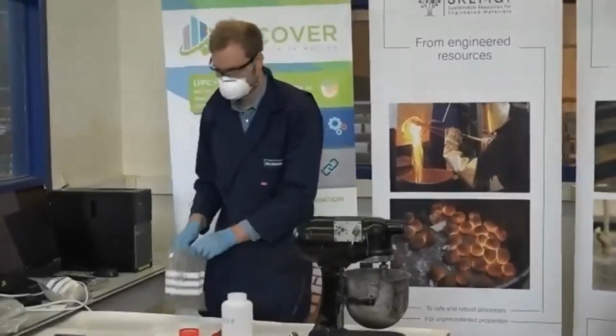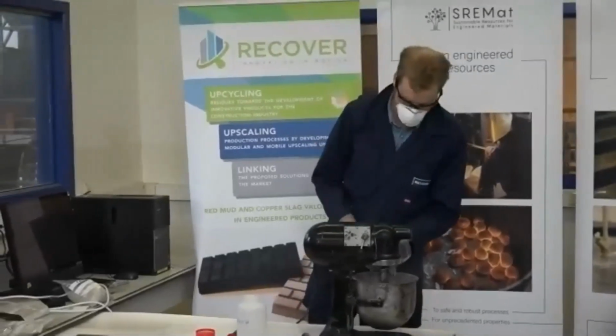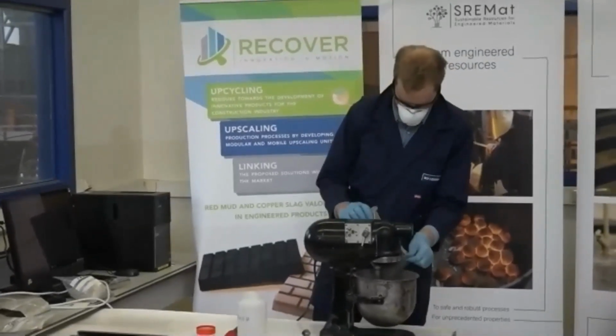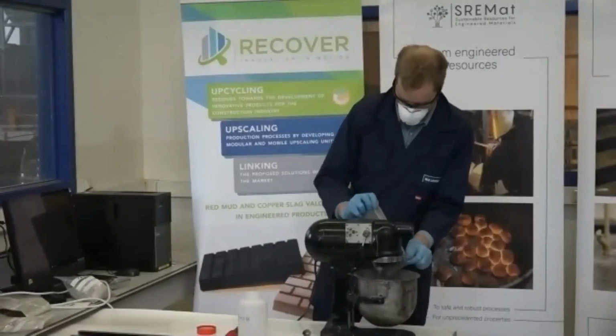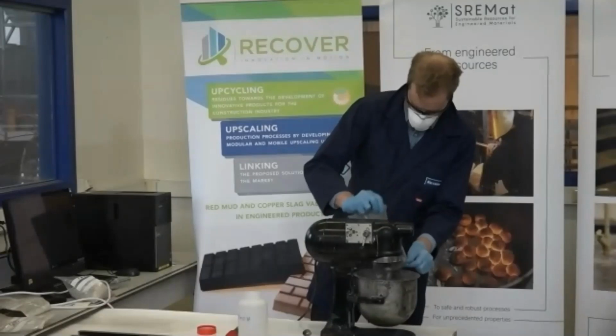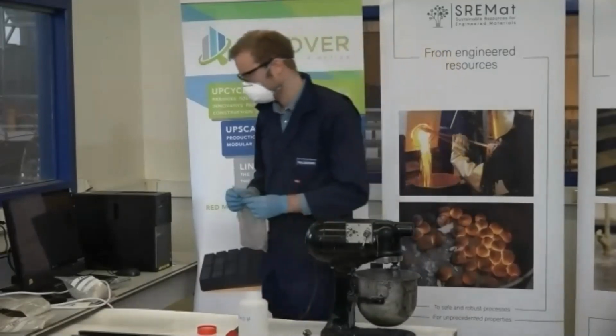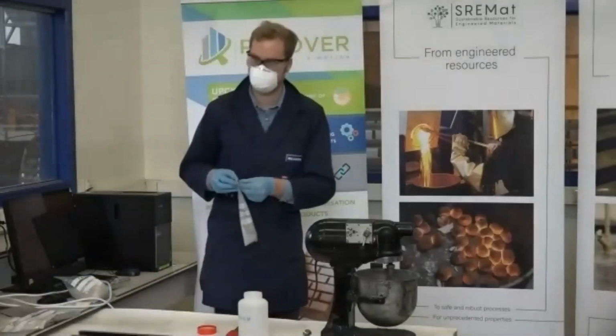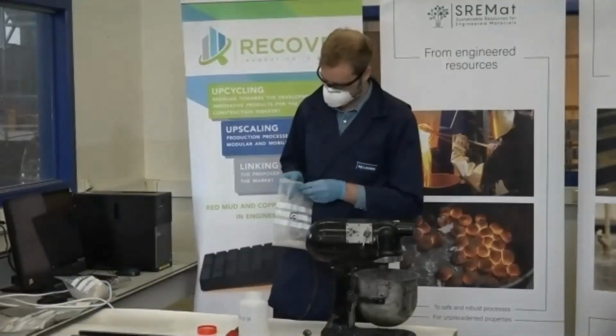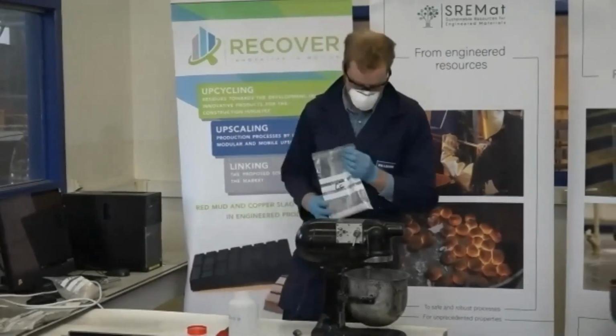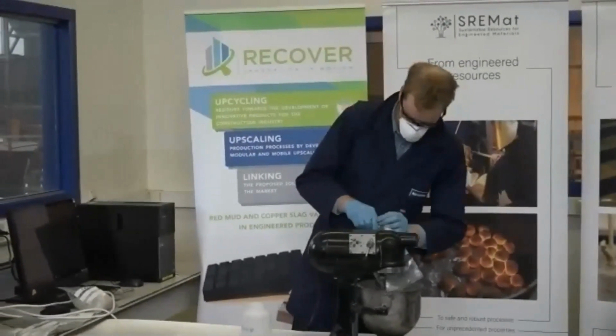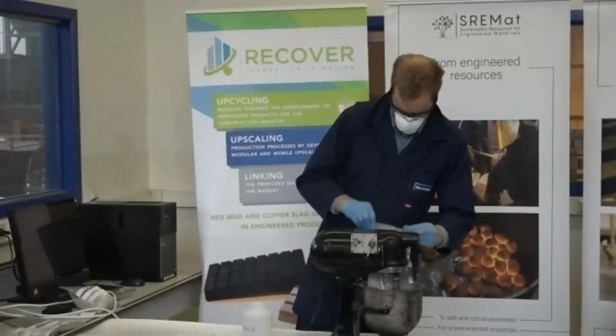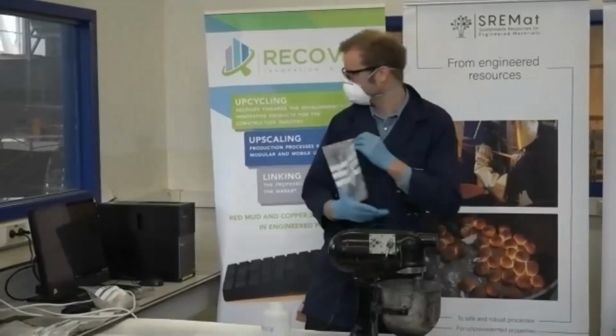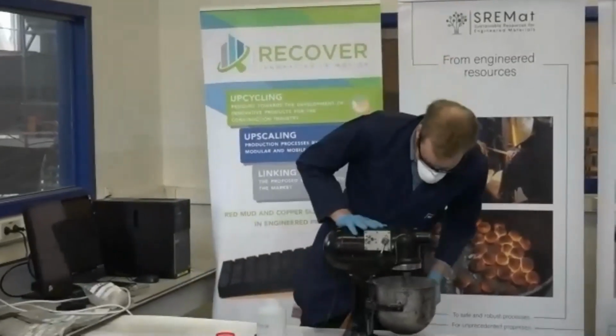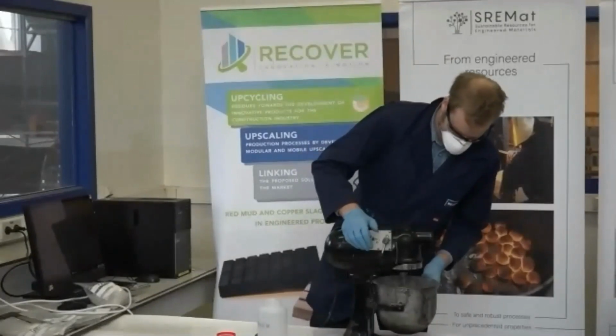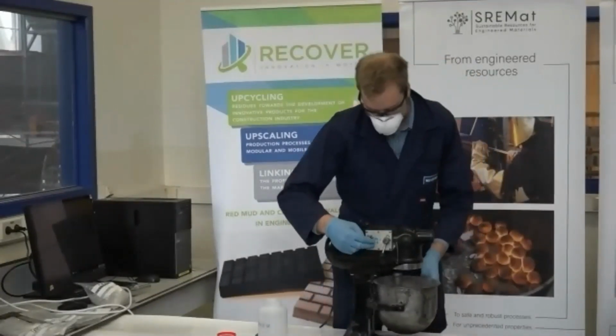And the main precursor, as you can see also from the size of the bag, is in this case Coronel slag. As mentioned before, we could also use the Boliden slag or vitrified red mud or bauxite residue. These are basically the three binder components that we add to the mix with the alkaline solution. Now he adds calcium carbonate, so a limestone filler material. This is a very finely milled limestone, and we add this material to enhance the particle packing of this mix, and also to have nucleation sites for the binder product. So we can have more hydrates formed on that high specific surface.